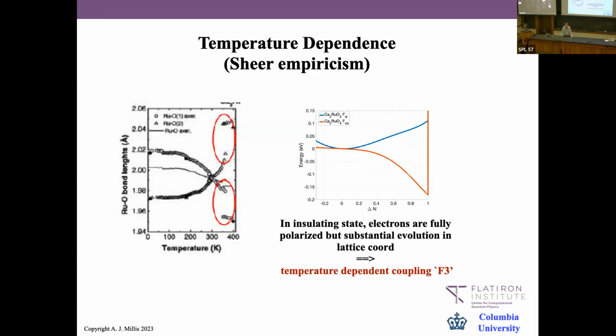With one exception, we do not have a good theory of the temperature dependence, and that would take me too far afield to go over in detail. But within the theories we know how to do, an electronic disproportionation drives a force on the lattice. Everything we know about the electronic disproportionation says it's essentially negligibly temperature dependent around here, but you can see that the lattice continues to evolve. So there's something funny going on that we haven't understood in the temperature dependence. And similarly in the other material I showed you, if we just run our machinery as a function of temperature, we predict transition temperatures a factor of 2 to 3 higher than they really are. I think we're missing some source of entropy for the high energy phase.